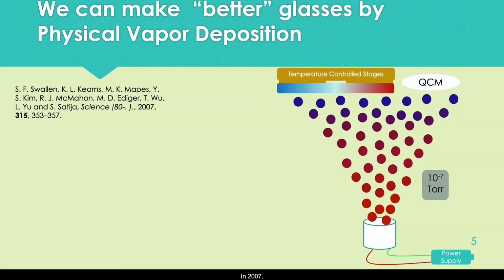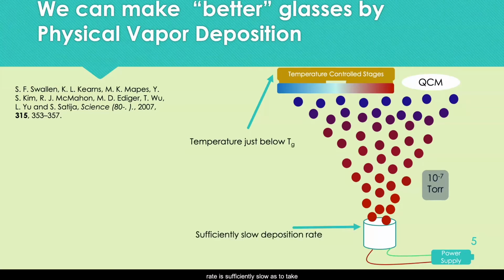And we do. In 2007, and you can see the original paper citation here, it was found that physical vapor deposition, or PVD, under particular conditions, can be used to create glasses which behave as though they were highly aged. Essentially, we go to really low pressures, heat the sample up into the vapor phase, and allow it to deposit onto a temperature-controlled stage. The important features here is that the sample substrate is held at a temperature just below TG, and the deposition rate is sufficiently slow as to take advantage of the enhanced mobility at the surface, so the most recently deposited molecules are faster than they are once they are buried deeper into the film.